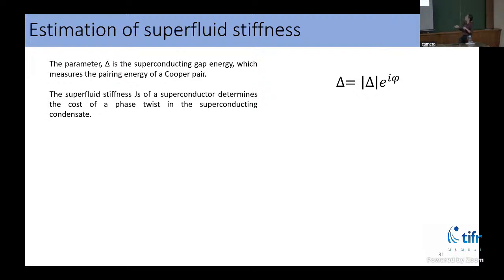One is if I apply so much more energy through the superconductor that it's greater than delta, and then the superconductor basically switches to a normal state. For example, if I increase the temperature and the temperature energy scale is much, much larger than delta, you have crossed the critical temperature. But I can also make it go normal if I just have many, many vortices in a type 2 superconductor. In that sense, I did not break this delta threshold of energy, but I just inherently included a lot of phase twist in the superconductor. Even in that sense, I am able to make a superconductor go to a normal state.